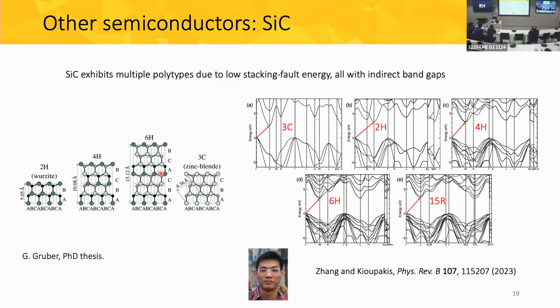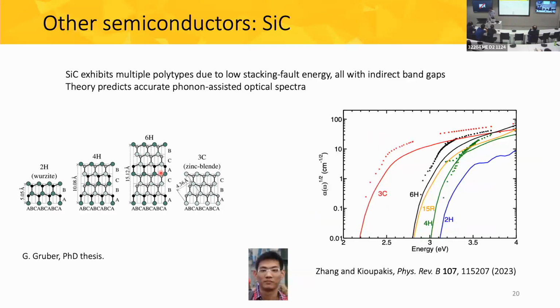And depending on the polytype you see, you get a different band gap value. All of them are indirect, but the value of the band gap varies with the stacking sequence. So we did just that and calculate the optical spectra, and we find again that we get a very good agreement with available experiments.